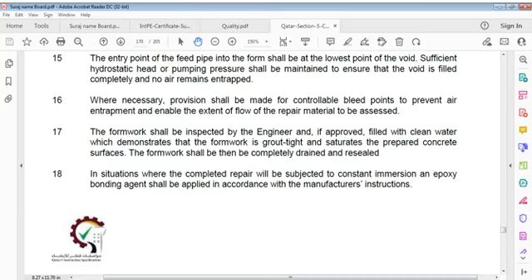Entry point of feed pipe into form shall be at lowest point of void. Sufficient hydrostatic head or pumping pressure shall be maintained to ensure that void is filled. Where necessary, provision shall be made for controllable bleed points to prevent air entrapment and enable extent of flow of repair material to be assessed.